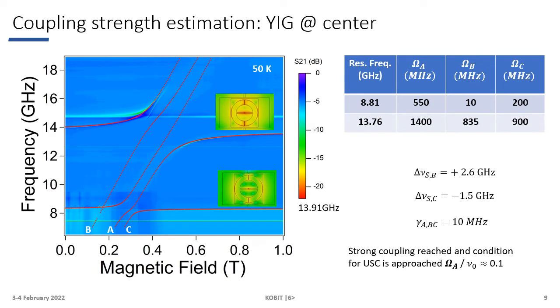The fitted coupling parameters are shown in the table, and the line width of the magnetic modes is also obtained, around 10 MHz. And as expected from the field distribution map, the coupling between the inverse anapole resonator and Yttrium Iron Garnet occurs just between the 8.8 and 13.8 GHz modes. We are in the strong coupling regime, and the condition for the ultra strong coupling regime is being approached by magnetic mode A and the 13.8 GHz mode.